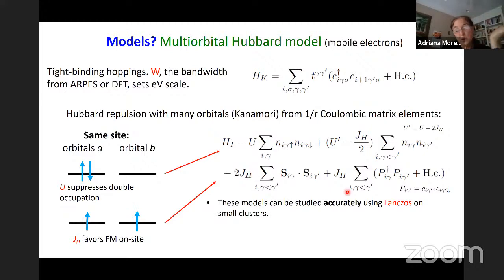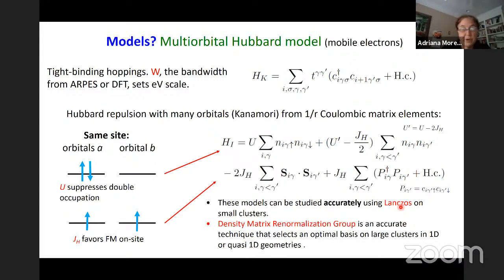So the most accurate technique would be Lanczos. The problem with Lanczos is that we can work in very small clusters. So an approach that will allow us to work in larger clusters is DMRG, density matrix renormalization group. The problem with the approach is, well, it's excellent, but it works very well in one dimension or in quasi one-dimensional geometries. So the question is whether we can go from the plane geometry to something simpler in order to study these multi-orbital models.